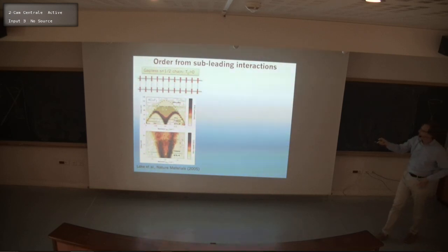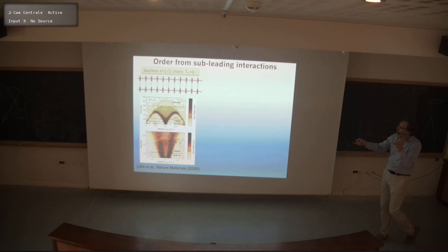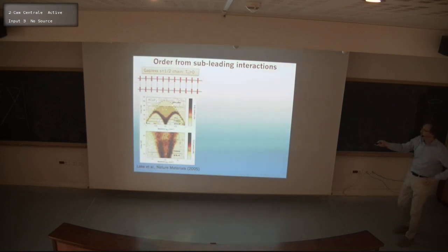And that happens, for example, in the case of potassium copper fluoride. It doesn't really impact the high energy excitations. Those still look pretty much like spinons even in the ordered state. But if you go to sufficiently low energies, you'll find that the spinons in the ordered state are actually bound together, and two spin half particles then form a magnon type excitation. And so you get additional branches in the really low energy regime, which are your spin wave type excitations. So this can all be seen experimentally, and there really is a phase transition into that state.